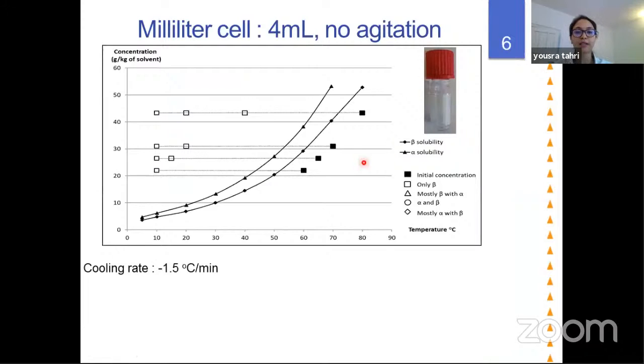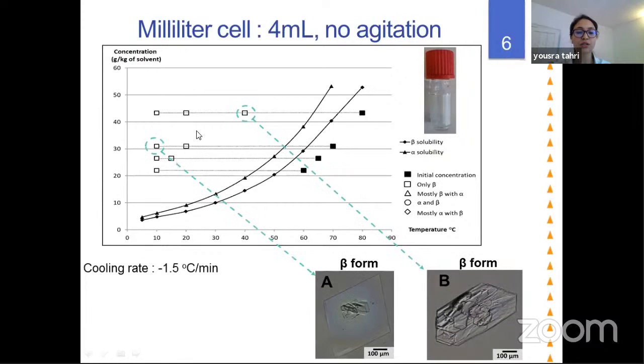So we investigated different operating conditions in the 4 milliliter cell. We always started undersaturated, then we cooled, and we waited to see which crystals appeared. For all the experiments that we did, we only observed the polymorph beta, but depending on the supersaturation, we observed different crystal habits. For higher supersaturation, the crystal habit was lozenge slabs, which was at the beginning surprising because it was similar to the alpha phase, but actually no, the X-ray confirmed that these lozenge slabs were beta. And then at lower supersaturation, we could observe the usual crystal habit of the stable phase beta.